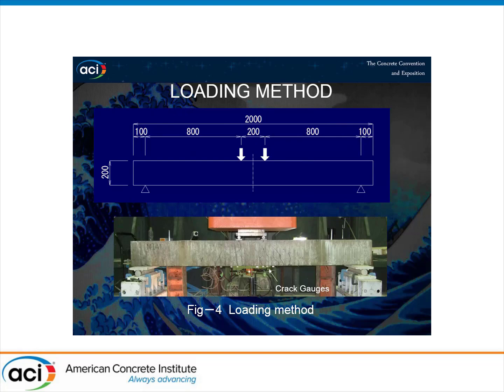This figure shows the loading method. The length of the specimen is 2 meters, the support span is 1.8 meters, and shearing span is 0.8 meters. The initial load before the exposure was applied to introduce crack at the age of 2 months, equivalent to about 60% of the flexural capacity. At the age of 3.7 years and 17 years, a load was applied again. The crack reopening load was observed using crack gauges, and a comparison made with the pre-cracking load observed at initial loading test.